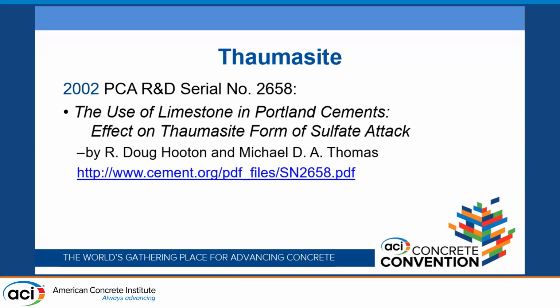Throughout the literature search, they discovered that there were no cases of thaumasite sulfate attack related to the use of limestone in Portland cement, which was something our members cared about, as well as this data supported the proposal to permit the use of 5% limestone in Portland cements, which then became the ASTM C150 change. So this was a very important beginning work.